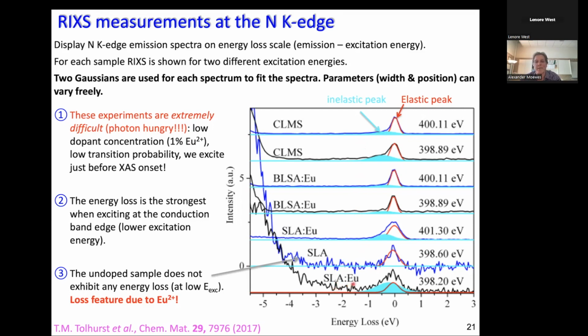So when you compare doped and undoped sample, although very statistically noisy, we say that there is no loss feature in the undoped sample here. And that tells us that this feature, whatever the energy loss is, it has to do with europium, with the dopant. So now the question is, what you see here always, you take this to be at 0, and then there's something like a half or 0.3 eV, there are these losses. So what happens is you have photons coming in, you have photons coming out. These photons have a reduced energy by about 0.3 to 0.5 eV. Now, the obvious question is, what is this due to? So that's what we are after.